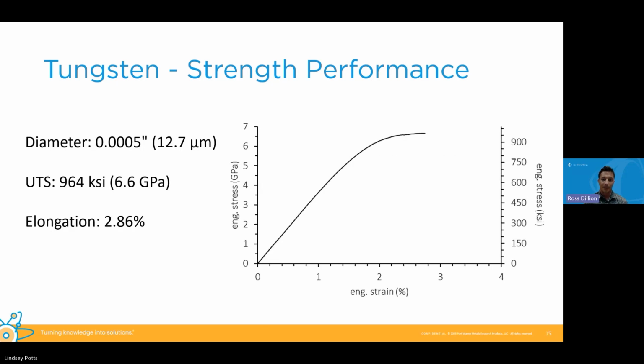As I noted, the 800 plus, this is where that plus comes in. We're able to almost hit 1,000,000 PSI at 12.7 micron in diameter. And still, again, maintaining excellent elongation. So this is basically the highest recorded strength that we could find for commercially pure tungsten.